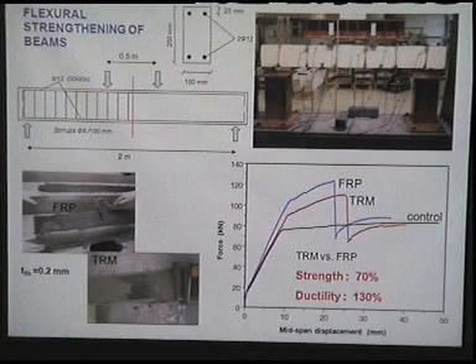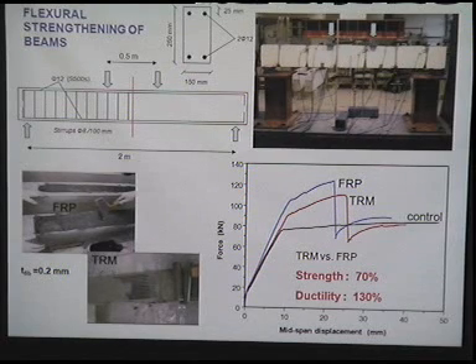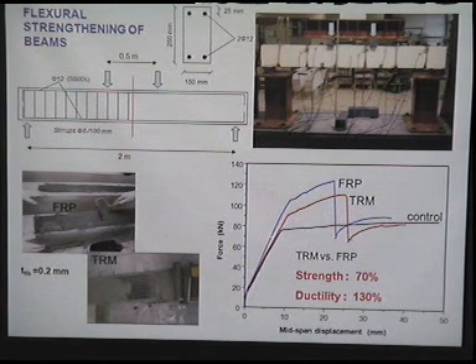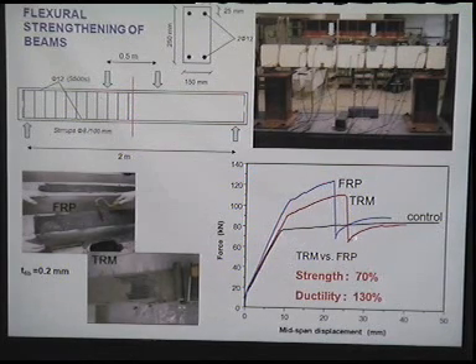The next set of experiments dealt with flexural strengthening of beams. In that case, the reinforcement was bonded externally on the tension zone just below those beams to increase the flexural capacity. A typical response of a member without flexural strengthening is the one shown by the black curve. We see force versus mid-span displacement curves here. So this is the beam before strengthening. Blue illustrates how that identical beam would behave after flexural strengthening with FRP, and red is the corresponding curve for the case of strengthening with the TRM system.